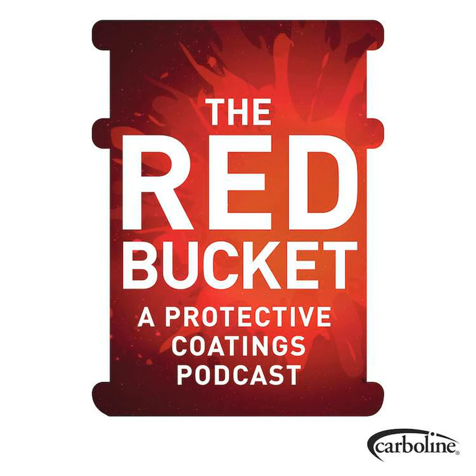You really need to teach your customers, your potential customers, that when you're trying to save energy, when you're trying to save BTUs, you will have a slightly decreased performance over brand new traditional insulation. But in turn, 5 and 10 years down the road, when you're starting to see corrosion under insulation, which starts with having moisture in the insulation, which degrades the insulation value, 10 years from now, you could have a better insulation performance with an insulative coating than with a mineral wool style conventional insulation.